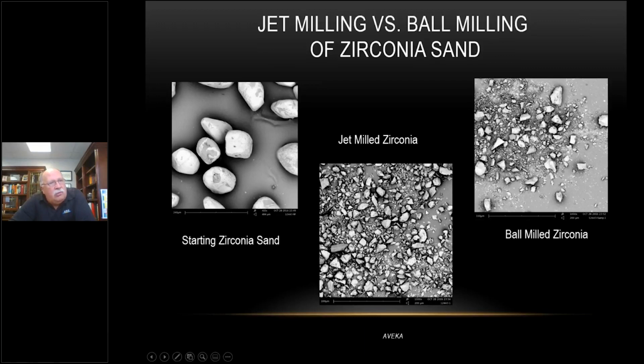But if fines were an issue, and they were in this particular case, jet milling turned out to be the better process. That's just kind of given us this idea of why we would want to do jet milling if it is more expensive: because we can control that size distribution and do a little bit better on that fines generation.